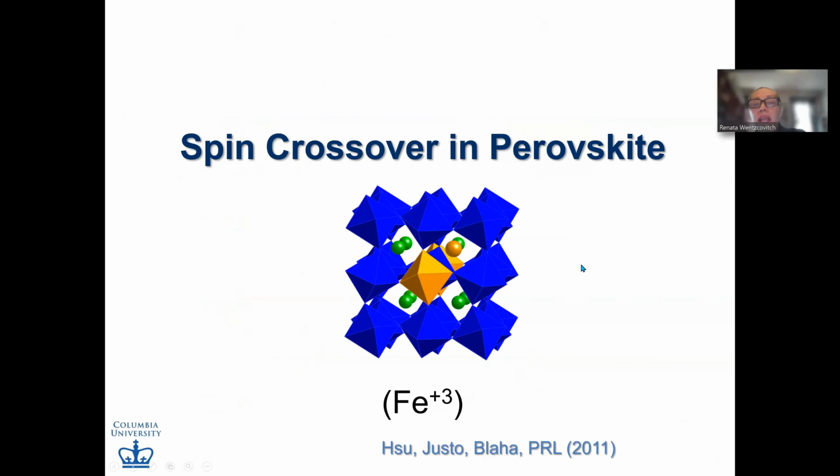So that's it. What happens in this case: ferric iron also has a spin state change from high spin to low spin, like ferrous iron in ferropericlase. It's exactly the same situation. And ferric iron in this site doesn't have a spin state change either. This is all the way high spin, five electrons with spin up, no change in electronic configuration. So for the purpose of understanding the elasticity of rocks, unless you have ferric iron in the B site, this is not going to be important.